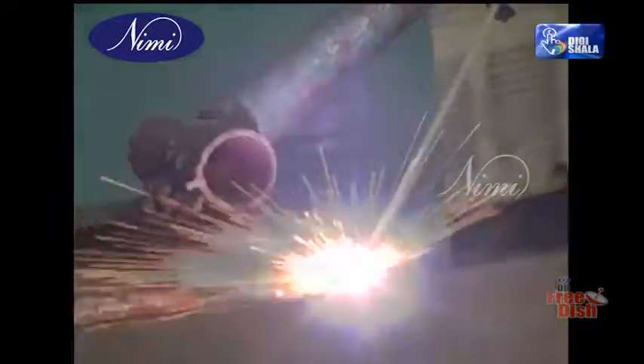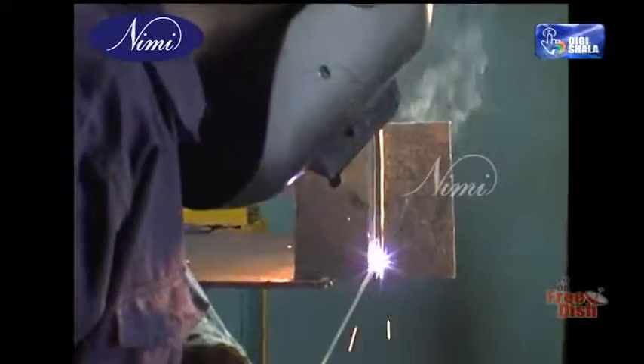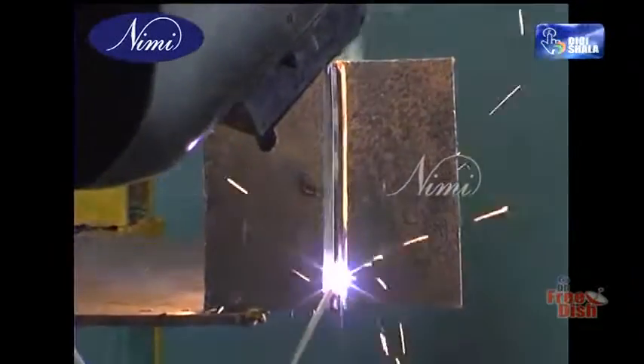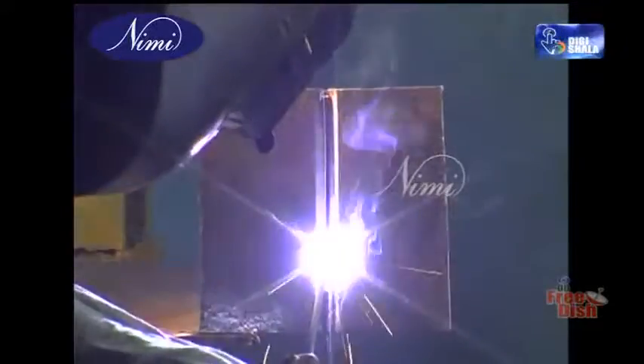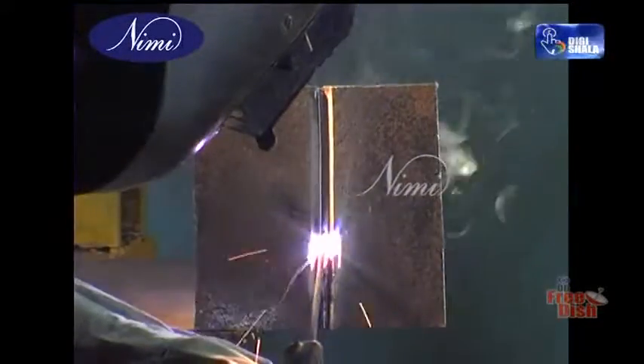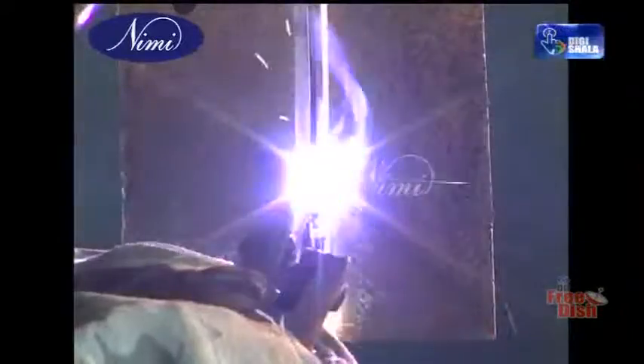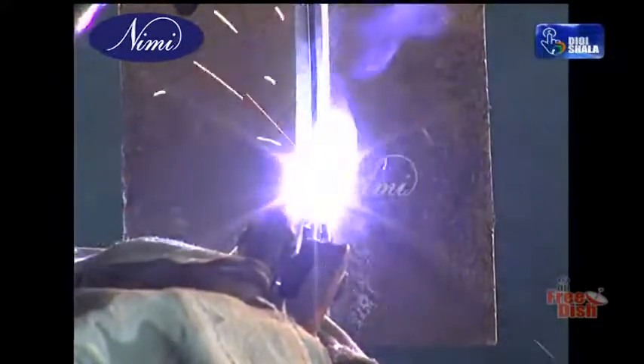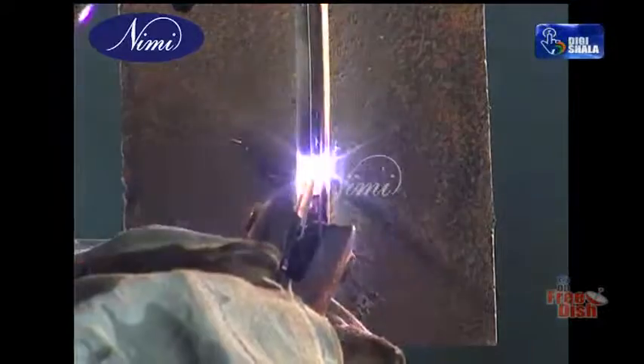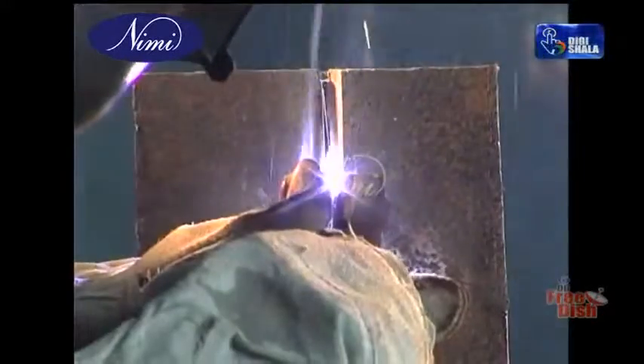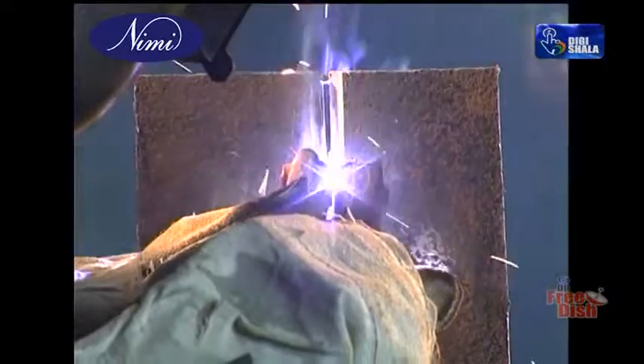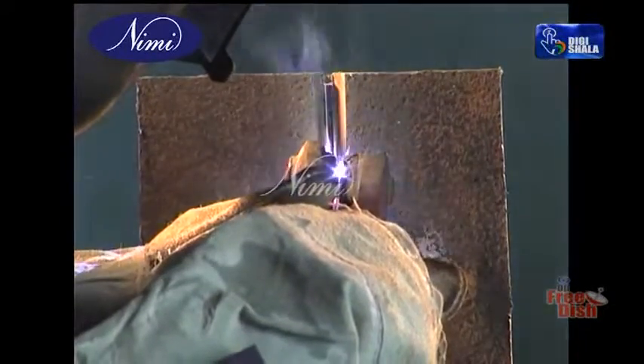We check the arc by striking in a separate plate whether the setting is okay or not. Start welding from bottom to top, that is uphill position. One thing I have to remind you, when you are doing a vertical welding in an uphill position, that is starting from the bottom to the top, a slight change in the current will be required. Previously you have been welding in 100 to 110 amperes, but when you are doing a vertical welding, you may set the current at reduced amperage. It can be around 90 amperes. If you require, you reset the current and start the welding.